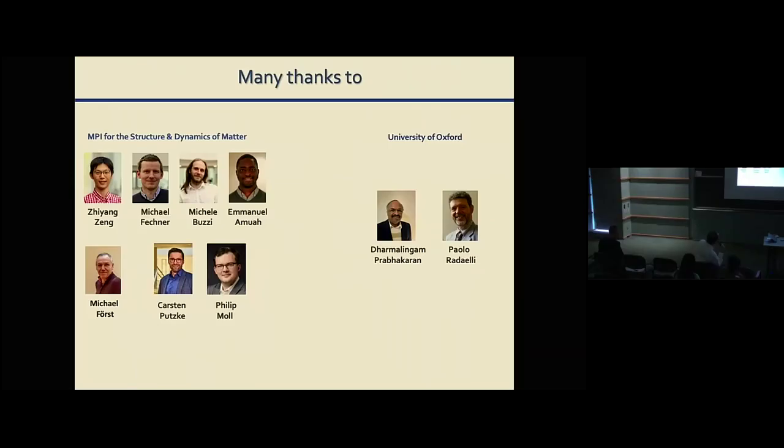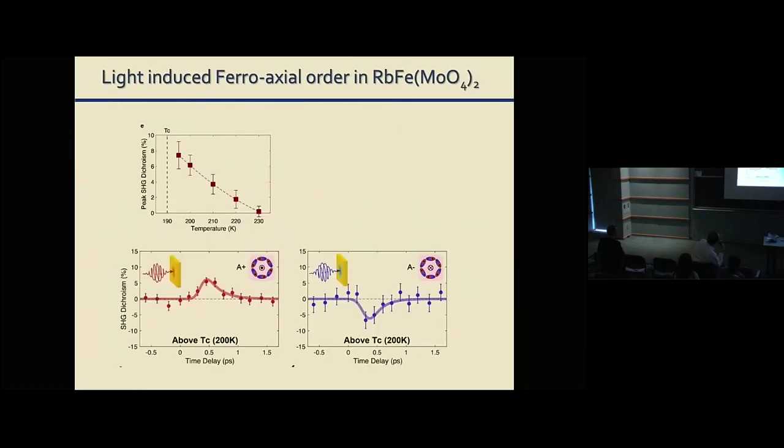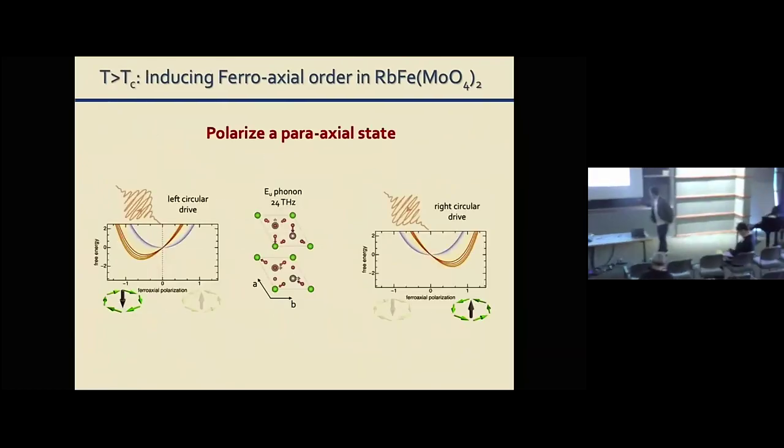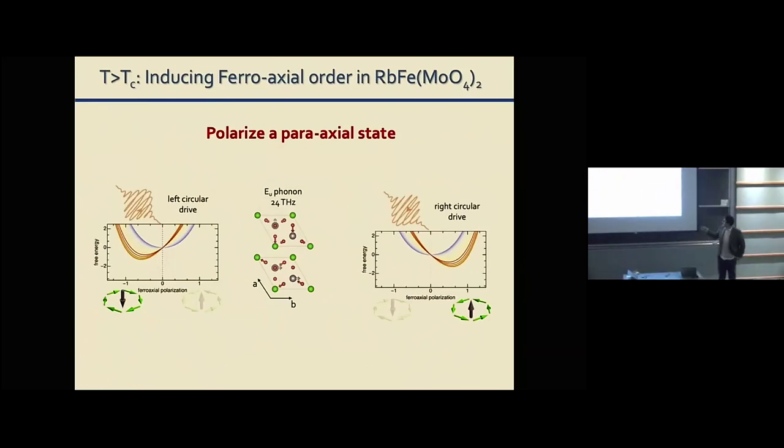For a beautiful talk. For this last part, I didn't quite. What are the specific conditions that you need for your laser, like wavelength and intensity? Well, in the specific, I forget where the E sub u mode is. Let's see, maybe I have. There you go. 24 terahertz. 24 terahertz is a high frequency axial mode, and there's two of those. You need two to generate rotational modes. So this is pretty high frequency. It's pretty straightforward. 24 terahertz is about 12 microns.